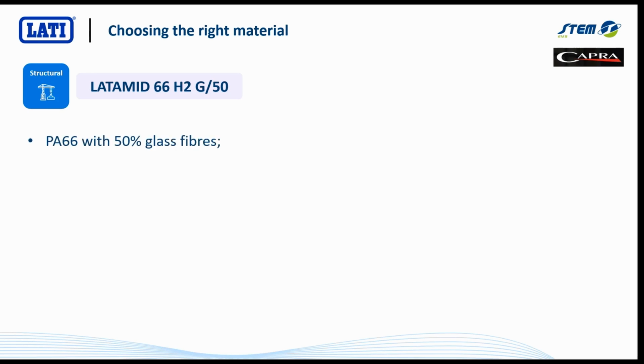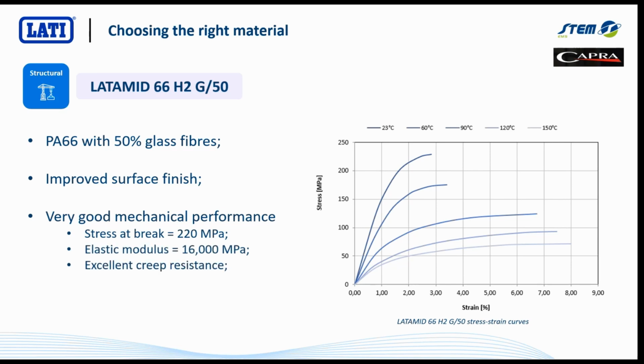Step one then is choosing what we think would be a suitable candidate material. And I think fairly obvious looking at the mechanical requirements. We're looking at something from within LATI's structural material range. And the material that we opted to open with here is a material we call Latamid 66 H2 G50. So this is a nylon 66 with 50% glass fiber, amongst other things in there. It's a grade with improved surface finish. It's a grade with very, very good mechanical performance. So strength of above 200 megapascals, modulus around 16 gigapascals, and it does have the excellent creep resistance